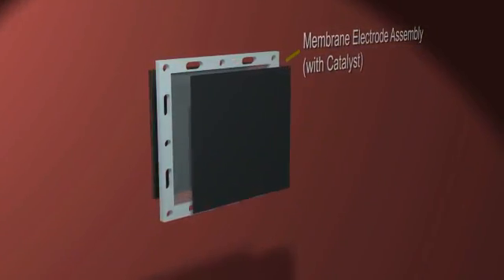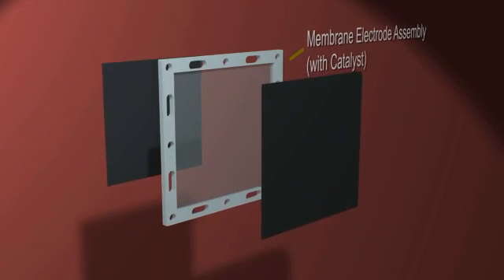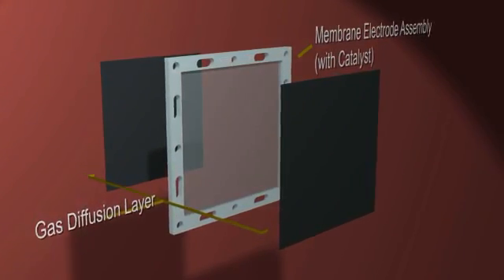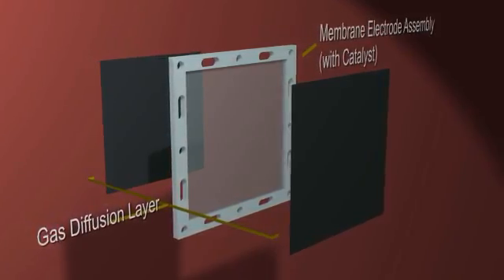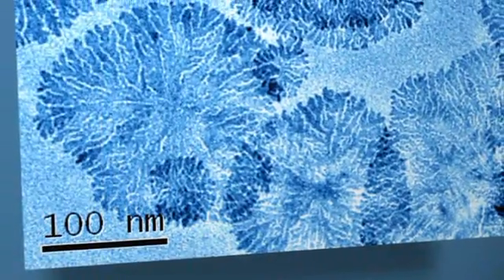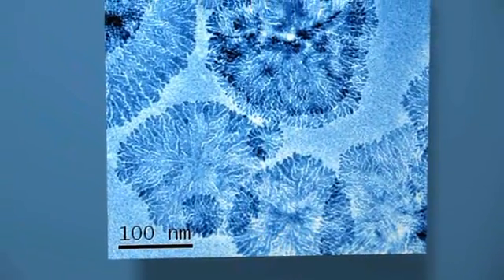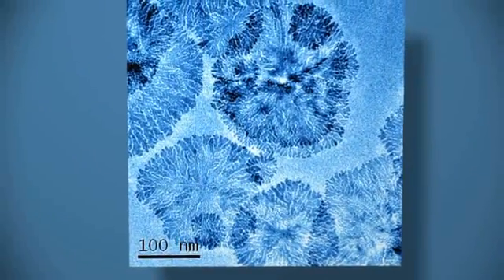Sandia's team has discovered new ways to control the growth of platinum that enhance the activity of the metal surface where catalysis takes place. Their approach is to replace typically used platinum nanoparticles with nanosheets that have this special property and are only about eight atoms thick.